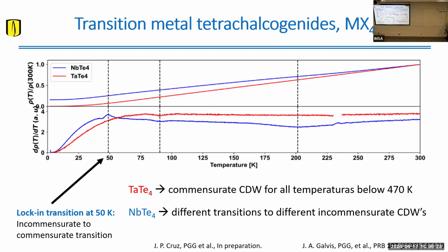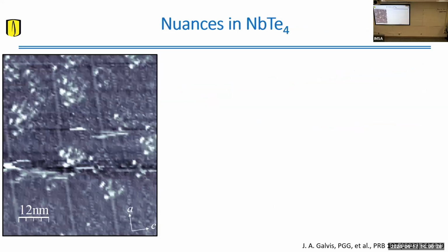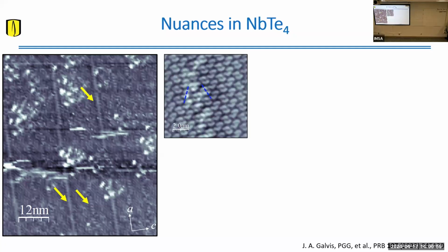So the first thing we did was characterize the charge density wave right at this low temperature. Let me show you some extended version of these STM measurements. We took larger area images and we noticed, don't pay attention to this dirt here on the surface, what is important is the lines, the things that go below that, which have some atomic periodicity. If you check these lines here, these look like columnar defects or domain walls, which are domain walls in this material.